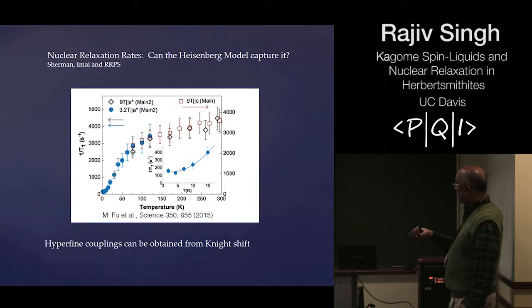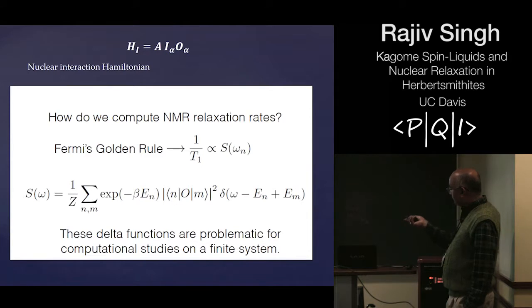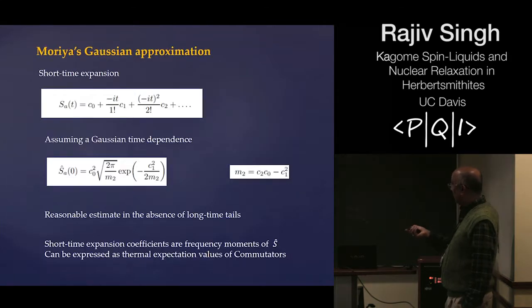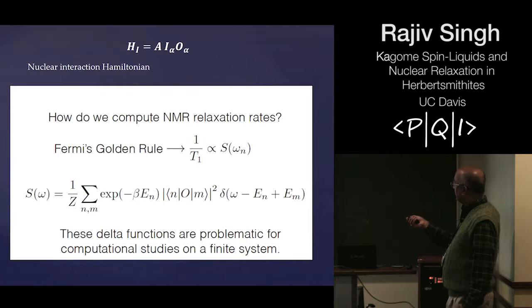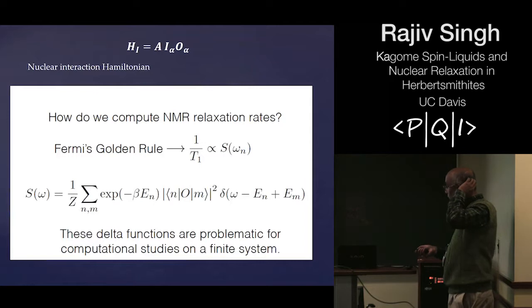What we have done more recently, working with Takashi Imai, is basically calculate the nuclear relaxation rate, but in the interest of time I am just going to be very brief over here. If we know the way the nuclear spins couple to the electronic spin degrees of freedom, the nuclear relaxation rate can be related to the autocorrelation function of the spin variable. But the nuclear relaxation frequencies are very low, so essentially we are interested in the zero frequency limit.